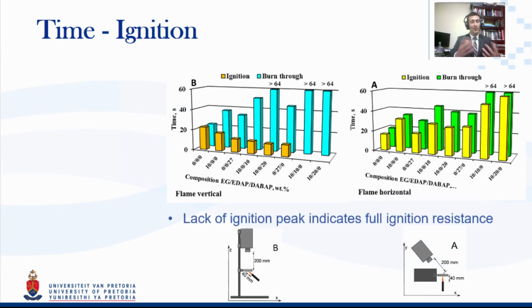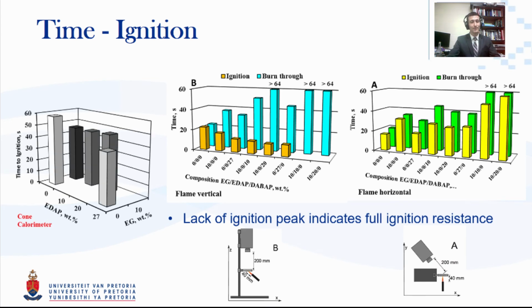Now, one of the other things we looked at with the open flame fire testing is the time to ignition. And here you'll see that we actually had some where no ignition whatsoever occurred. And those are the binary systems of EDAP and expandable graphite. So this is a really, really great result, because what this means is that expandable graphite has changed completely from its base behavior, where it expands as these loose strings that are readily available for attack, that even in the attack from below, in the middle here, it could not actually ignite. Whereas in previous studies, expandable graphite always ignited, further fueling the flame, further causing those negative gravitational effects.